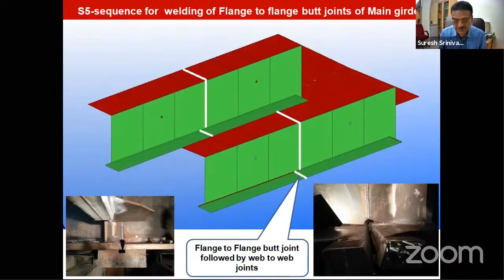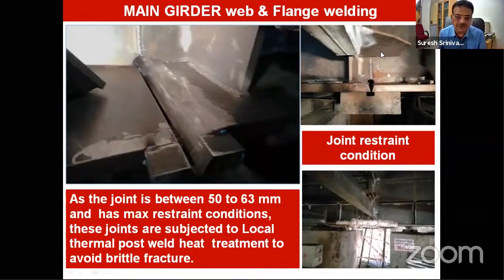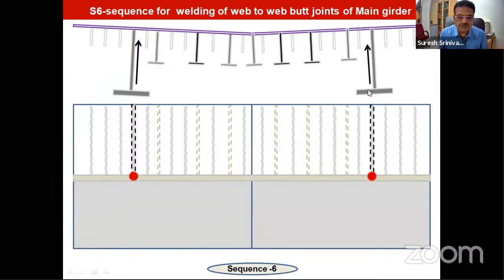So we did the stress relieving of all these joints, especially this joint, what you see here, especially above 50, we had to go for it, because the joint is under heavy restraint condition, the residual stress is likely to be active in all the three directions. And if you take a small weldment from this weld, it will be subjected to a triaxial stress state. So this is what we did here. So all the welding directions are also seen here.